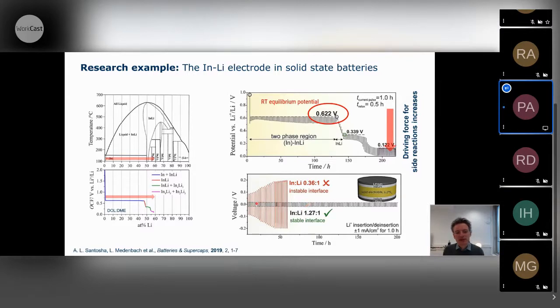You're in the two-phase region, then you have a very stable plating and stripping of your solid-state cell. And if you put too much lithium into your indium electrode, then you have a rapid increase in resistance, so in impedance, and therefore your battery performance will be very bad. So always when you assemble these cells, try to remember that you should not put too much lithium onto your counter electrode, otherwise your experiment might go wrong.